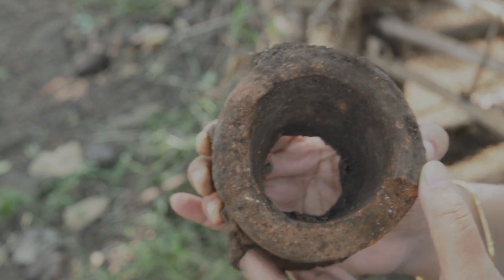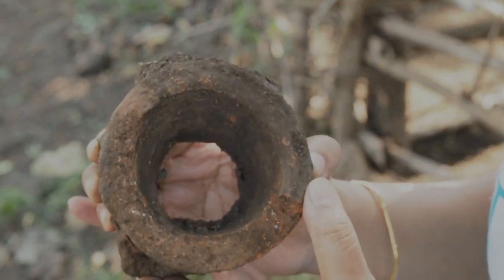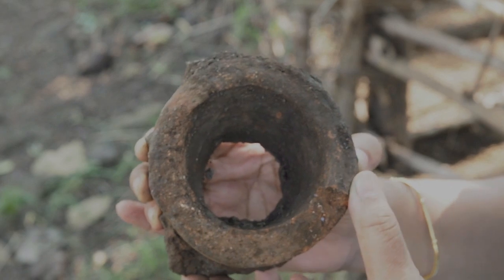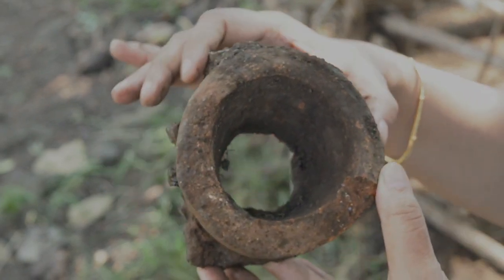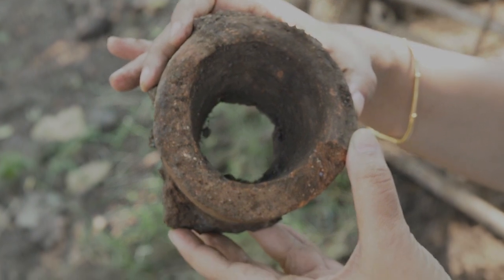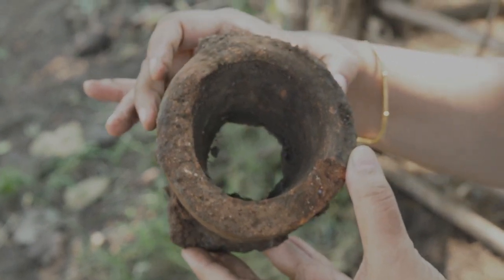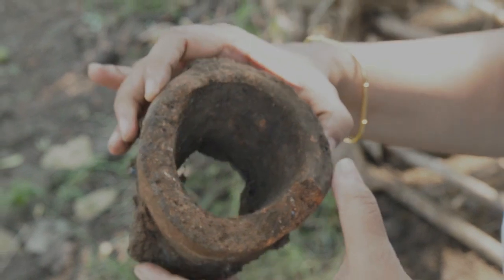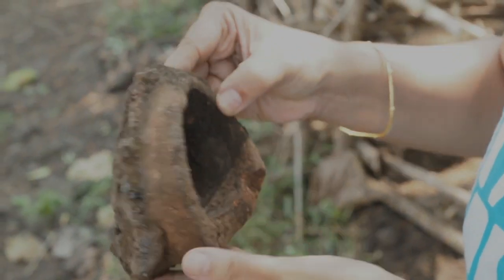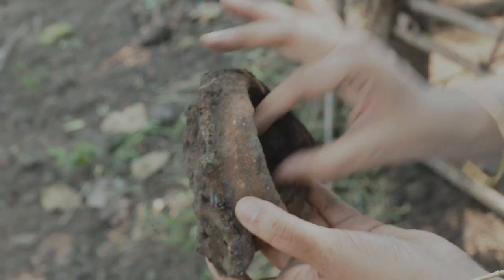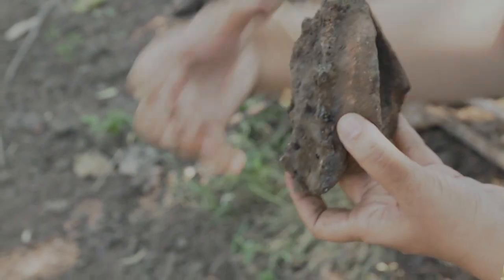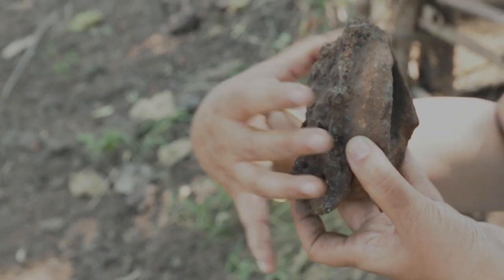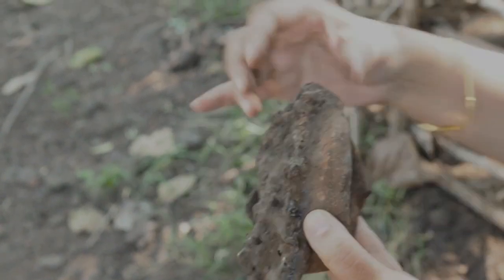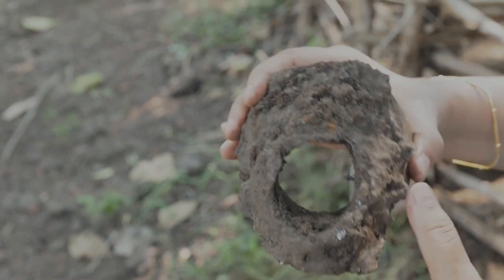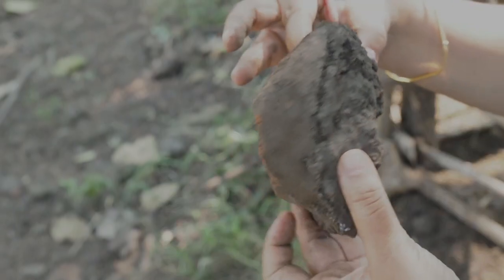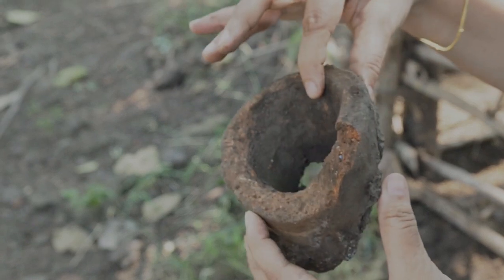So normally at these production sites we rarely see evidence of the finished metal, but we find a lot of archaeological debris like this. This is a specimen of a tuyere from this smelting site at Kalleda in the forest area in northern Telangana, and this would have been used to fix the bag bellows with which to blow the air into the furnace. This part would have been embedded inside the furnace wall and the furnace linings, which is why you see the slag all over this area. And this portion shows you that it's made of thick terracotta pipe.